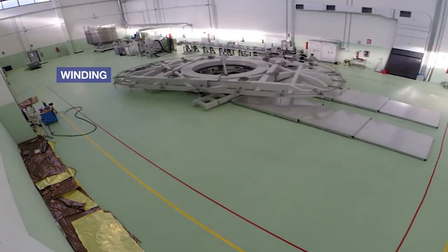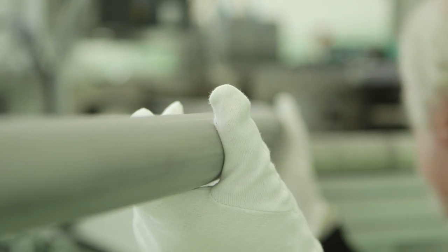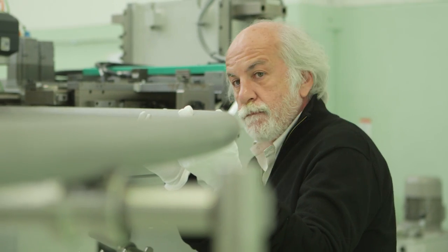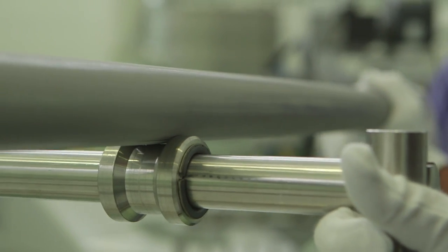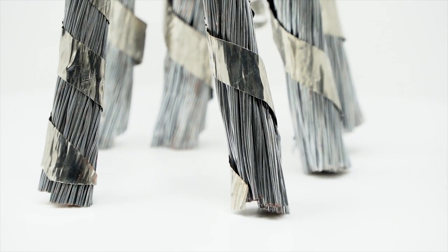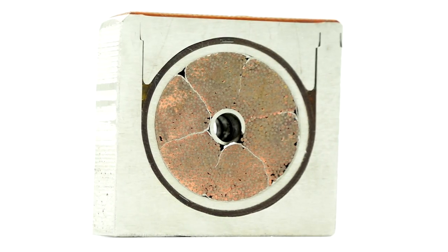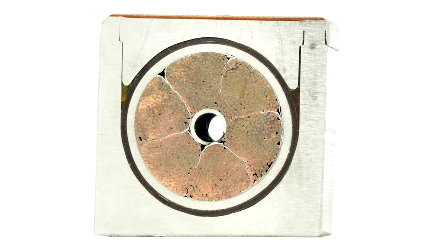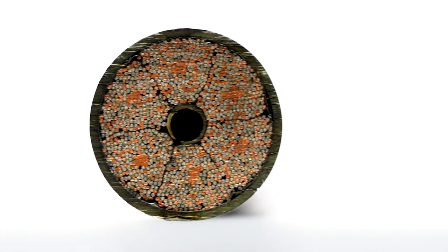750 meters of conductors are bent into a double spiral trajectory to form a double pancake. The length of the conductor during winding needs to be controlled with an accuracy of 0.05 millimetre per metre. The conductor is formed by a cable of roughly 1,400 superconducting niobium-tin and copper strands fitted inside a stainless steel conduit of about 45 millimetres in diameter.